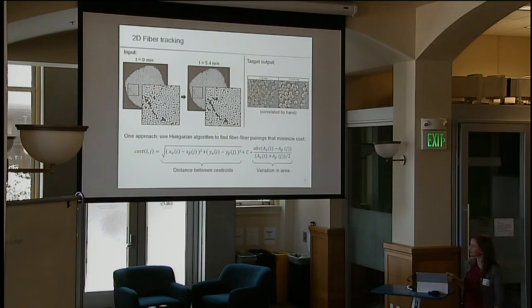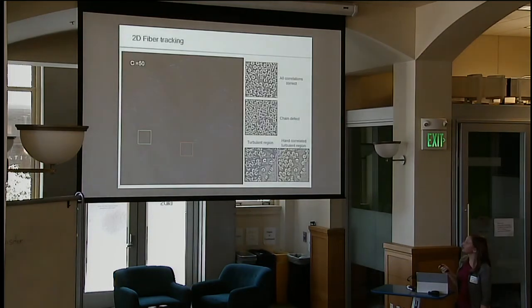So the cost matrix that I've developed is based on the distance between the centroids of any two fibers, and then the variation in area. Ideally, a small fiber is still going to be a small fiber later on. And then there's a constant here that I tried varying to see which parameter is more important. So these are the results so far. It's challenging to see up here. But the best results we found are for a value of C equal to 50.